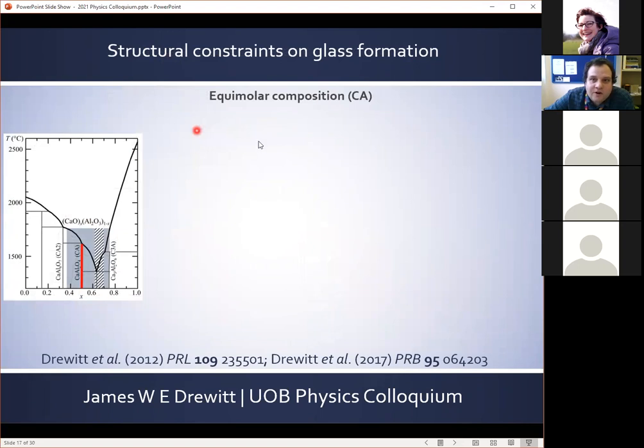So to summarize the structural constraints on glass formation in this calcium aluminate system, first for the equimolar Ca composition, we observe a significant fraction, around 20% of the aluminium, in highly coordinated AlO5 units, which comes with a significant fraction of oxygen triclusters, which are incompatible with glass formation. So this explains why, under ordinary circumstances, the equimolar composition doesn't form a glass.